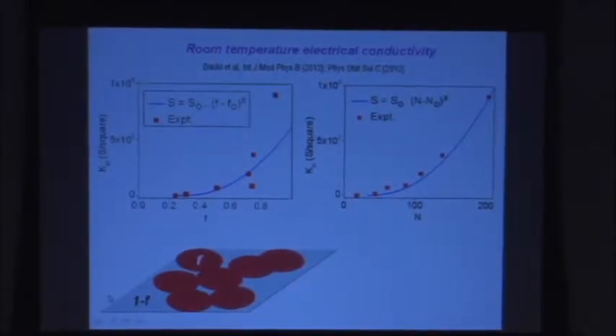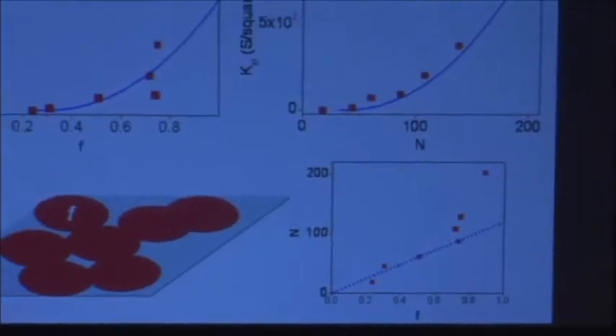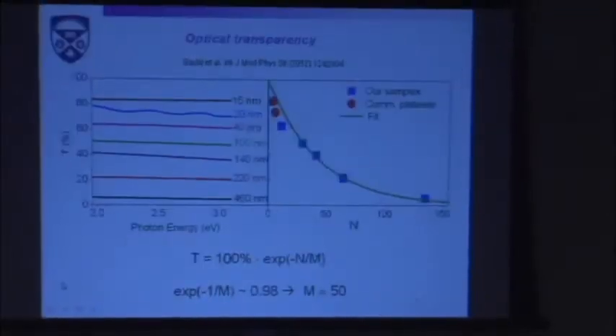This is a remarkable consequence of the vacuum filtration system, because the more I am filtrating, the more layers I'm piling up. Not only am I covering more area and decreasing the amount of voids remaining between the flakes, but I am piling up many more layers. In fact, between F, the fraction of covered area, and N, the thickness, that I can easily investigate with atomic force microscopy, for instance, or any microscope, or many forms of profilometry, I get something like that.